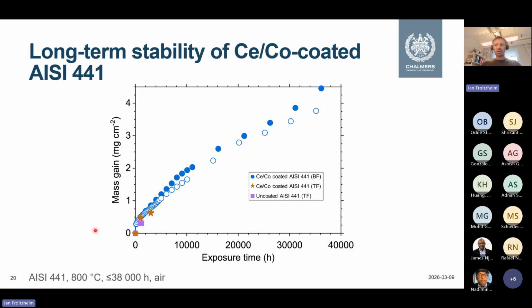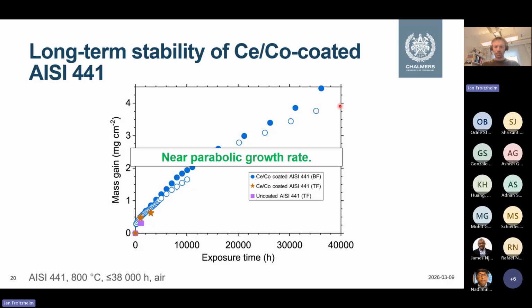3,000 hours was nice, but you want to operate your stack much longer than that. So this is data measured for up to 40,000 or 38,000 hours on 441 steel at 800 degrees C. You see the different batches, and basically what we call parabolic behavior: as the oxide scale grows, it becomes heavier, that's the mass gain we measure. Over time this is not linear, but it slows down in a more or less parabolic fashion. That's basically good, and that's what we want.